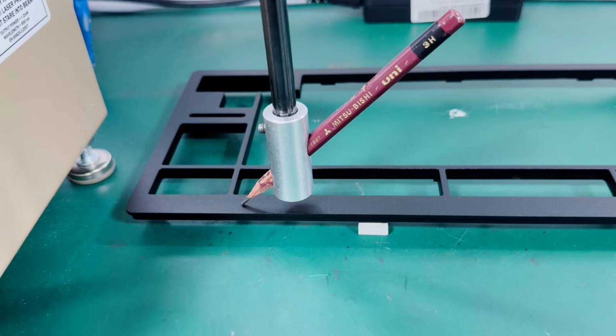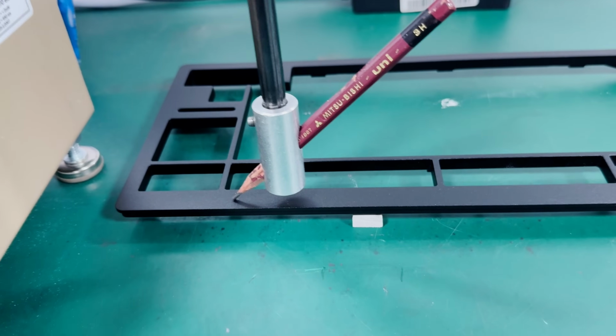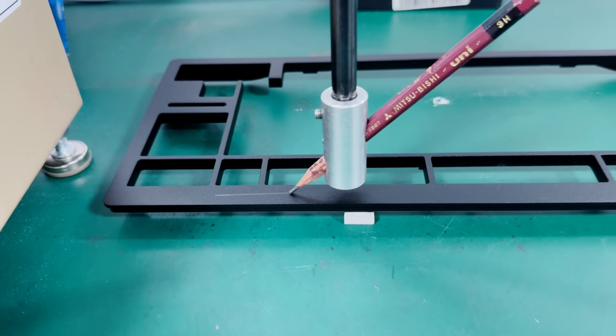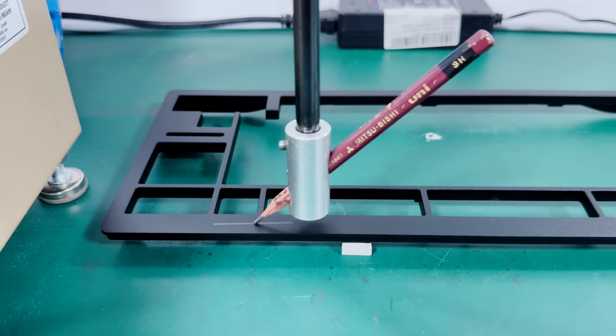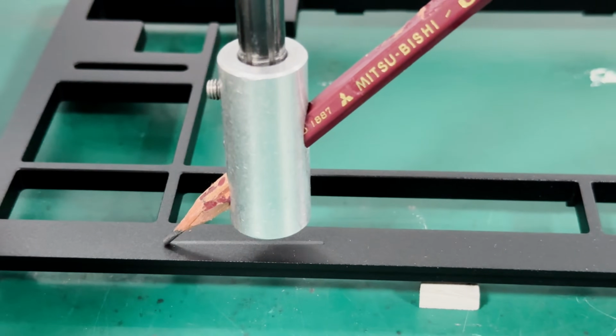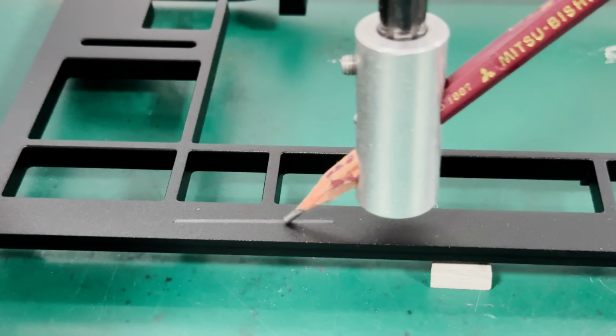And finally, and you might know this one, the White Zinc V1 version, where we had this gray mark stuff, we added a new test at that time also, which is called the pencil hardness test, where we literally have pencils of one specific brand with different hardness, and we go over the surface of the case and then see if it leaves any kind of scratch mark behind. Now, the Black Zinc case has gone through all these tests, passed all the tests according to our requirements, which are the same requirements we set for all our cases. But then the bowl test, the pencil test, and now also the sweat test that we're going to get into later have become new standards that we always require also with our coated products.